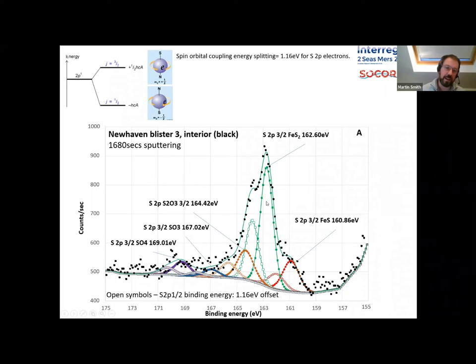Slight complication in interpreting these is that for each potential compound, we get two peaks. And I don't want to go into the physics of this, but that's essentially because of the spin coupling of the electrons within the orbitals, which means we get energy splitting. So we get two binding energy peaks for each compound. But with that, we can see in this, the interior of one of these accelerated low water corrosion blisters, we've got iron monosulfide, mackinawite, we've got iron bisulfide, pyrite, and we've got, very low down in the noise, peaks for thiosulfate, sulfite, and sulfate.